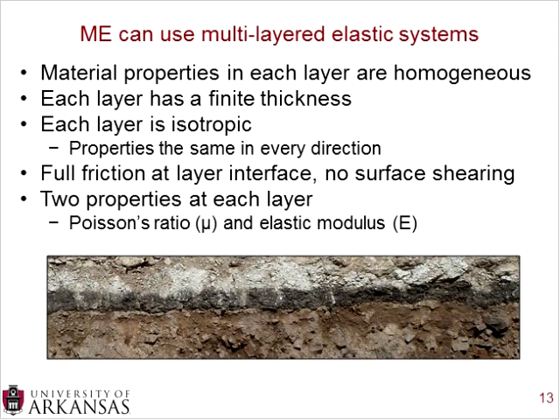And when you say isotropic, that means that the properties are the same in every direction. So whether you're looking longitudinally or transversely or down into the pavement depth, you're assuming that each layer has the same material properties. You're also assuming full friction at the layer interfaces. So that means between, as in this picture, the Portland cement concrete layer and the asphalt stabilized base layer, you're assuming that there'll be no slipping. There'll be no surface shearing or moving between those two layers. And the same between the asphalt stabilized base and the base course below that.